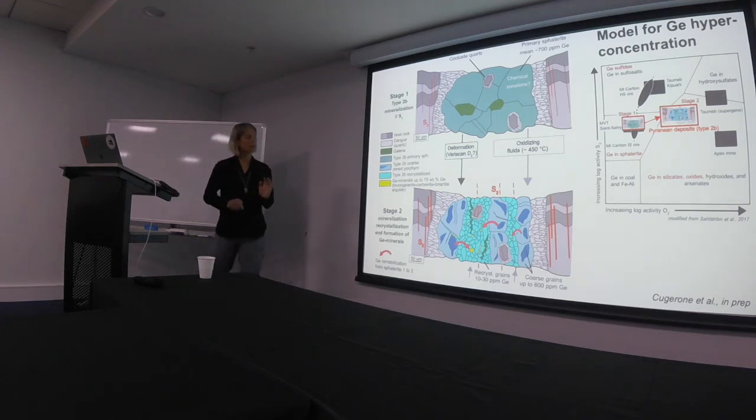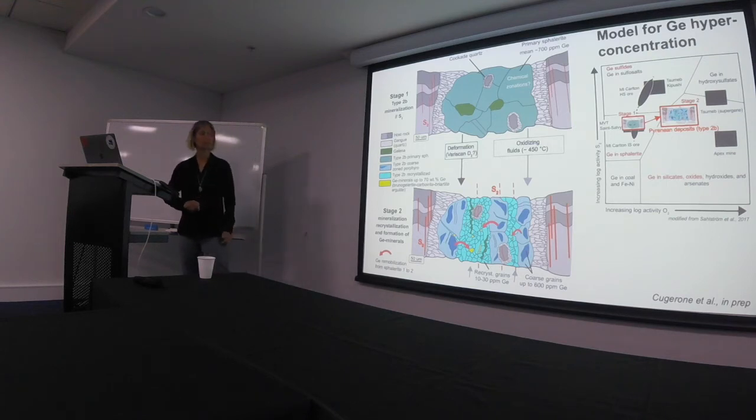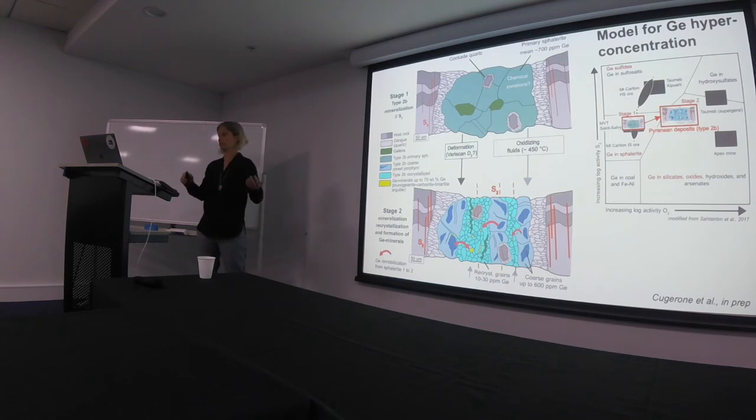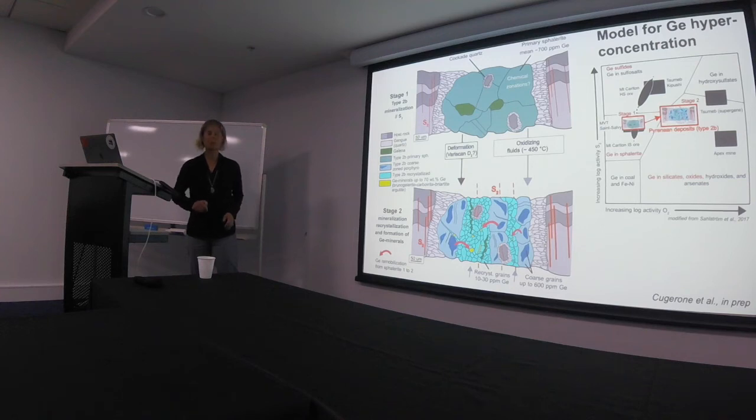The conditions are pretty difficult to determine directly, but indirectly, if we look at the latest variscan deformation phase, it is prehnite-pumpellyite phases. So something like 250 to 400 degrees at a low pressure. What's important to note is we probably need an oxidizing fluid.